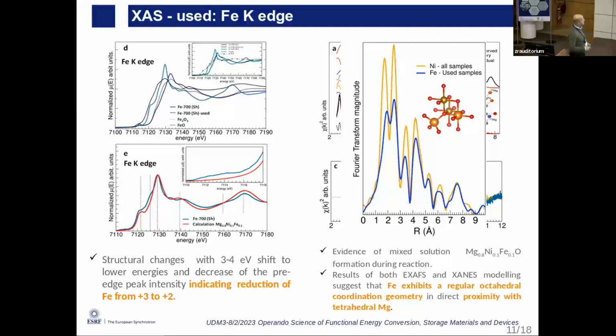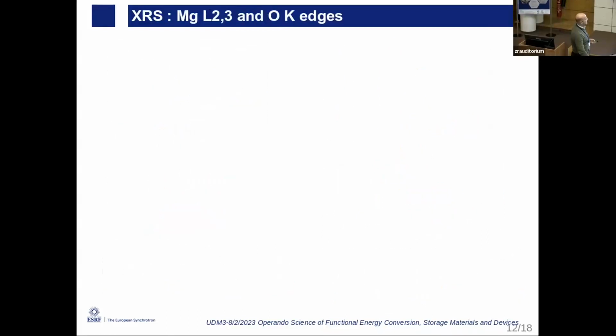So then from this kind of analysis, we can have a strong suggestion that iron goes into the structure, and it is basically replacing the magnesium, and the magnesium seems to be in tetrahedral configuration. By looking again at the pre-edge part, we can also see that from the simulation, we don't have a strong pre-edge that disappears after the treatment. So this means that the iron goes inside the structure. It is basically octahedral, quite symmetric, that seems to be in the oxide.